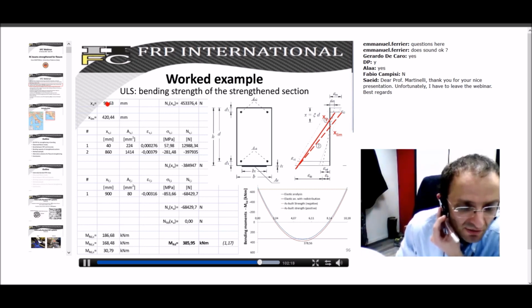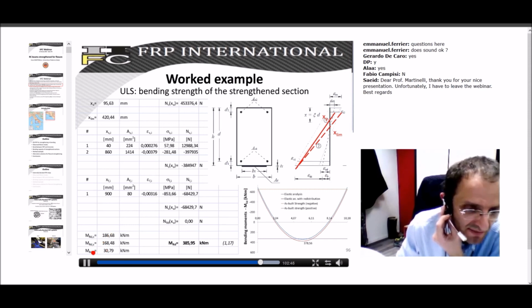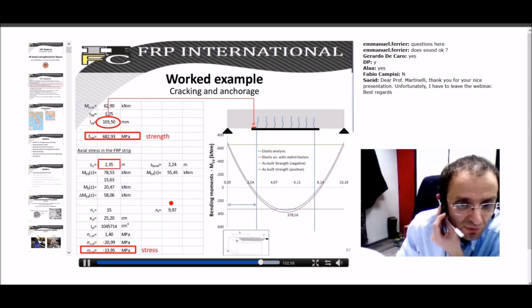So once we know XU, this is sufficiently high to confirm that the ultimate limit state is attained, because at the bottom the FRP is at the ultimate limit state. Then we have the contribution of concrete, of steel, and of fiber. This is a mistake here. This is fiber. So you have the contribution of concrete, the contribution of steel, the contribution of fibers. And this is 385.95, which is enough to